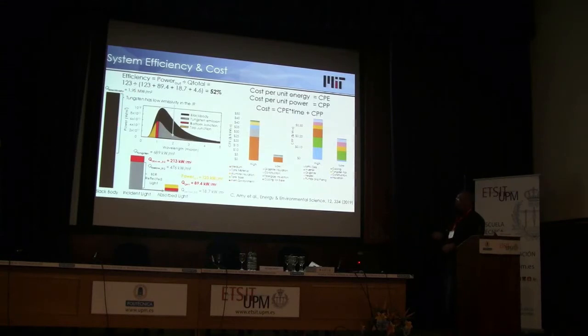But tungsten is a reflective metal. And so we get less than half of that coming out of the tungsten. So we pay a very big penalty using tungsten as the emitter, but from a reliability standpoint, I think it's our best choice. So we just accept that penalty. For the cells that we're using, only about 200 kilowatts or so would be above the band gap.